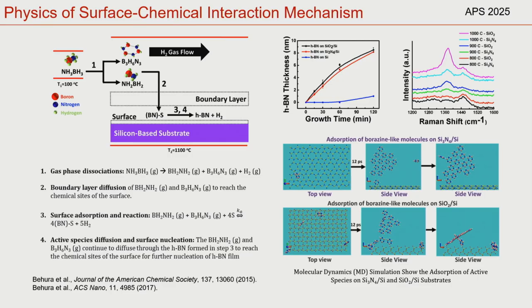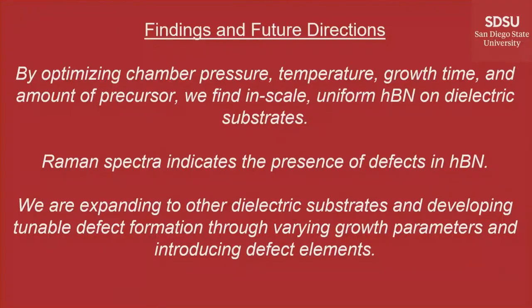Now, I want to point out a little difference, as you'll see in this graph here, there's a slight difference in these curves. Our lab has been playing both with silicon oxide as a substrate and also silicon nitride. And you'll see a slight difference here in the h-BN thickness over time. Now, we propose that the interaction with oxygen in the silicon oxide actually allows for faster growth deposition because of the very interaction in those adsorption and nucleation. We're going to be playing around with other dielectric substrates as well to further confirm this proposed mechanism for how it can actually grow directly on the surface.